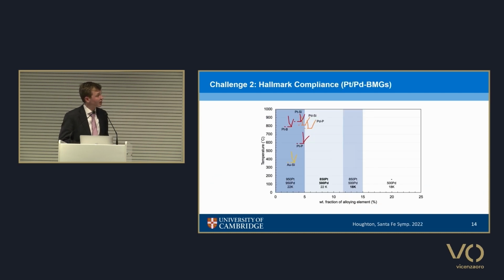The other issue is generally regarded as hallmarking standards or stamping regulations. So this is a bit of an expansion on the graph that Ulrich showed. It's to include the platinum and palladium and the gold systems. So for all commercially available systems at the moment, gold is preferable, largely because there's a much larger composition space to work within, thanks to the 18-karat hallmarking standard. But for our platinum and palladium systems, we're right at the cusp of this 950 hallmarking fineness. And so the large issue comes into considering that given that we need about 15 atomic percent metalloid or other additions to form a glass, we can only be using a certain range of light elements.